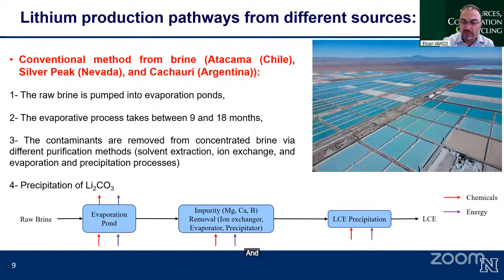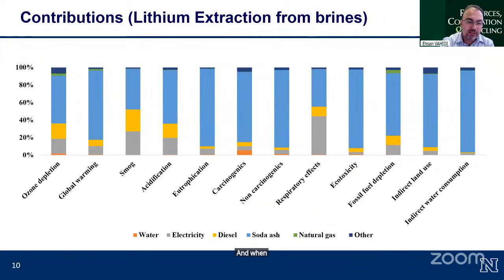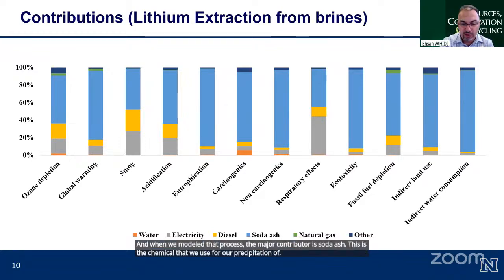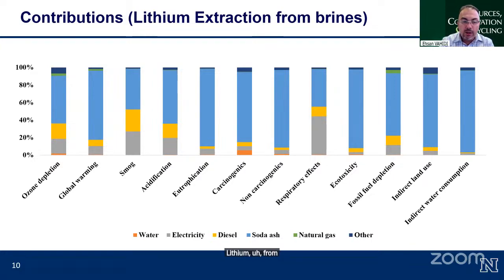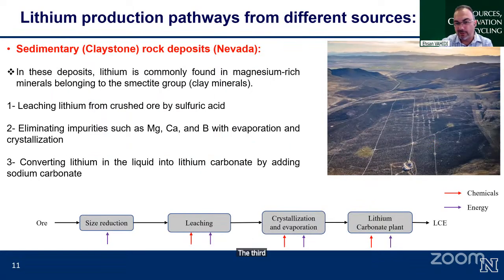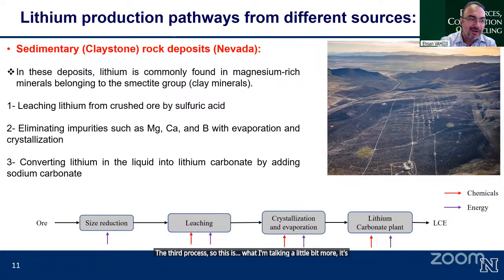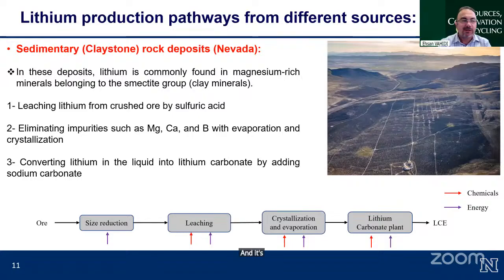And you can see again chemicals and energy in the process. And when we modeled that process, the major contributor is soda ash. This is the chemical that we use for precipitation of lithium from the solution and the production of lithium carbonate equivalent. The third process, so this is what I'm talking a little bit more. It's in Nevada, and it's a kind of new process. I'll talk a little bit about the status of the project in Nevada.